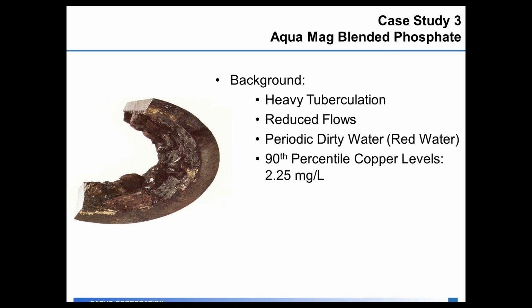Another case study, this case for Aqua Mag Blended Phosphate. The background of this plant was that they had heavy tuberculation in the system. They had reduced flows that impacted hydrant testing. They had periodic dirty water and red water complaints, and they had 90th percentile copper levels at 2.25 milligrams per liter, which was above the 1.3 milligram per liter action level.